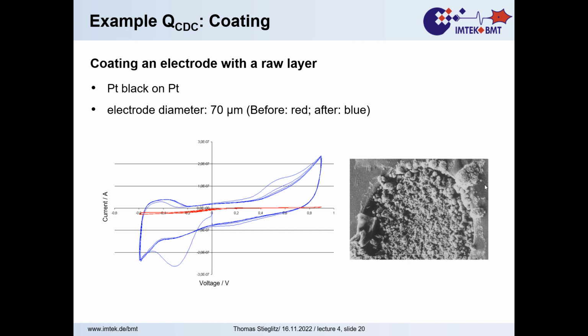And if we look on the curve, you can hardly see the red curve. That's the charge transfer, charge delivery capacity of platinum. And if we put that on top, we see a much larger curve for that platinum. It's so micro rough that it appears black in a light microscope, since it no longer reflects the light, and therefore it's called platinum black.